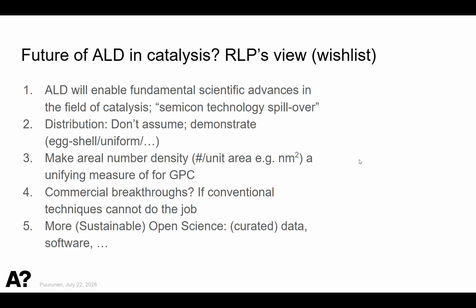For catalysis, it's important to pay attention to the distribution. I'm actually quite worried that there might be quite many papers out where people have assumed that you have a uniform distribution throughout, simply because it's ALD and ALD would give it. But if the process hasn't been tuned for that, then it might be that you have an eggshell only. So you need to demonstrate that, in my view.